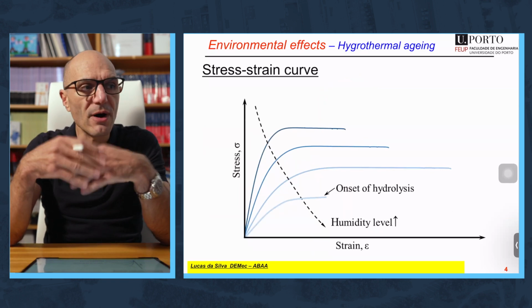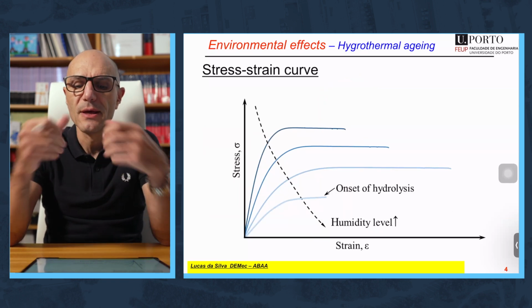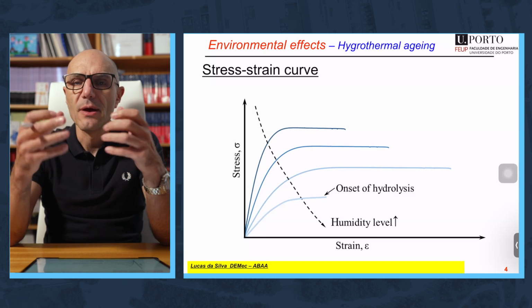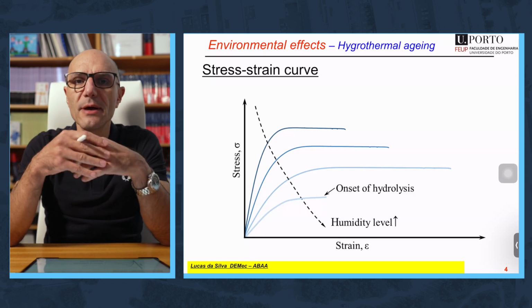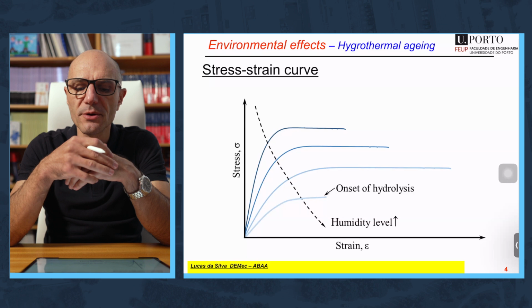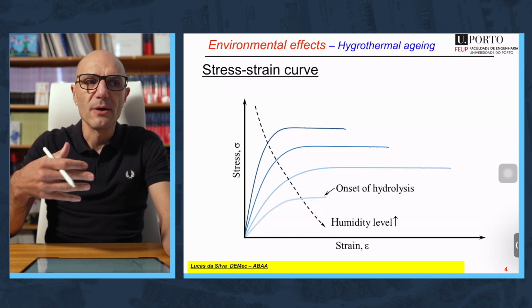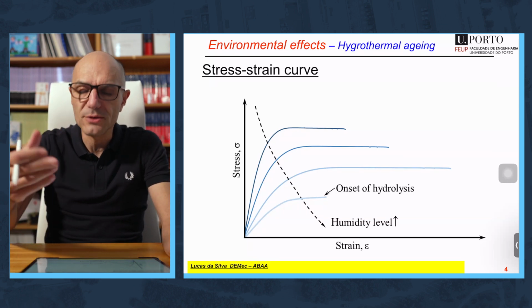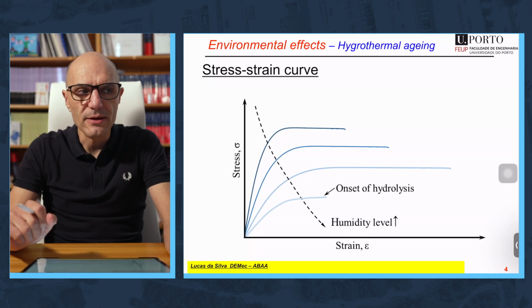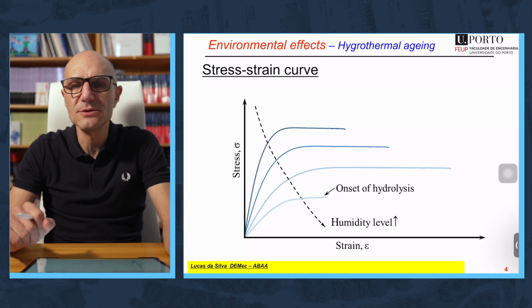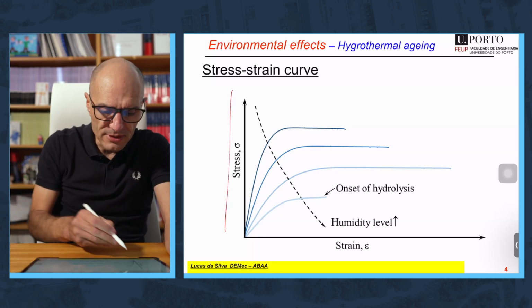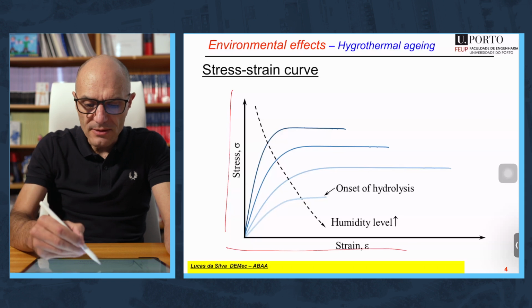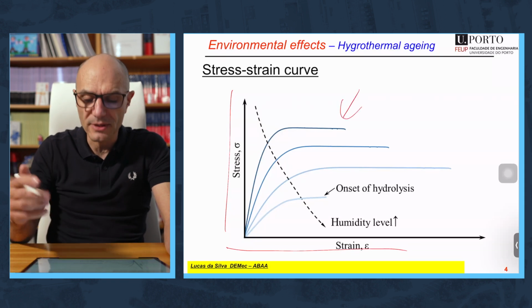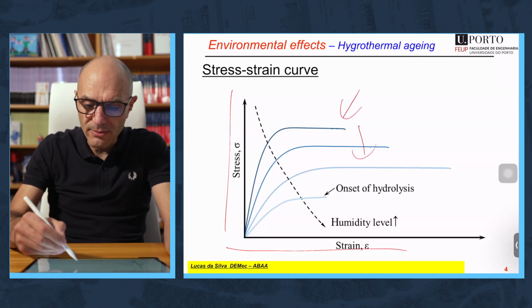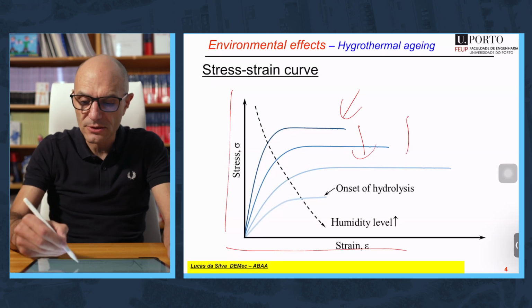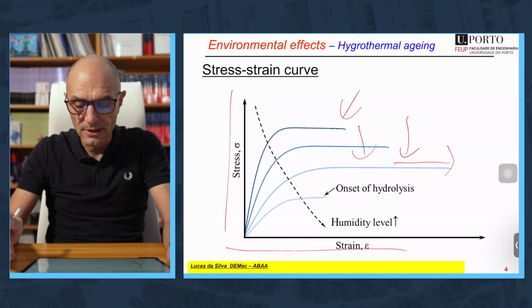It's important to know how fast the water goes in, but it's also important to know how the water affects the stress-strain curve. Then we need to take dog bone specimens, tensile load them, and see how is the stress-strain curve. You have here the results, stress, strain. This is the virgin material without any water. As you increase the amount of water in the adhesive, the strength goes down and the ductility goes up.